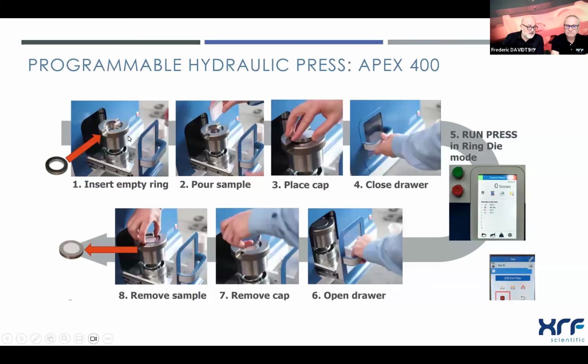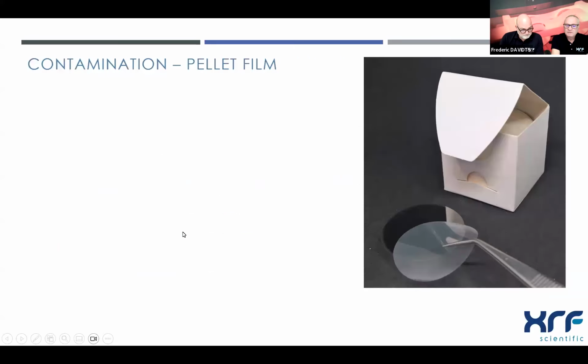So just to explain quickly, here this is the case of the pressing in the steel rings, but you can also press in aluminum cups or even without any support. So you load the powder, you put the cap, close the drawer, select the program, push start, and when you hear the beep after 1 minute 30 seconds, you can reopen the drawer and collect the sample after removing the cap. So it's really easy. You don't need to manipulate the die. So when you have high throughput, it's the best tool.